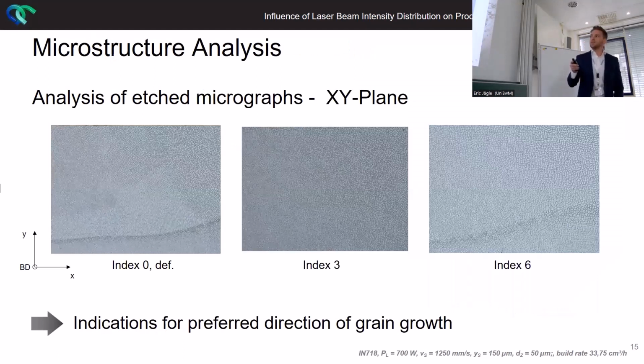One thing we then analyzed was the XY micrographs, and what we can see here is that on the left side, on the bottom, for index 0 samples, the grains are a little bit elongated in XY direction, whereas almost every grain here is kind of equiaxed for index 6 sample. And that was the first indication for a preferred direction of grain growth for us.